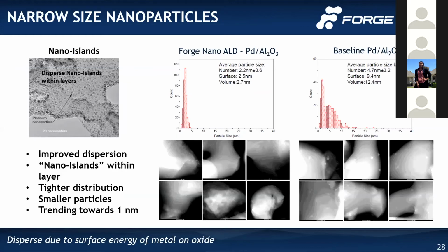For active metal deposition, this is work we did at Forge Nano for palladium deposition compared to a baseline like incipient wetness deposition. This histogram shows the particle size distribution. ALD gets you a very tight, narrow distribution of particle size, but incipient wetness can do really well at this too. So there are added costs that may not benefit enough to justify doing ALD for the active material, like platinum or palladium.